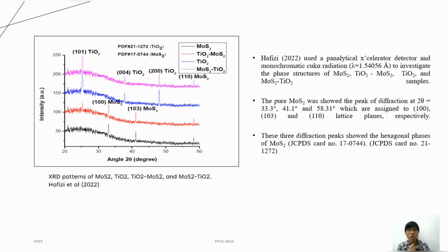Hafizi 2022 used a PANalytical X'Celerator detector and monochromatic radiation of 1.54 to investigate the phase structure of each material of interest. The pure molybdenum disulfide showed peaks of diffraction at 33.3 degrees, 41.1 degrees, and 58.31 degrees, which are assigned to the lattice planes 100, 103, and 110 respectively. And these three diffraction peaks show the hexagonal phases of MoS2.